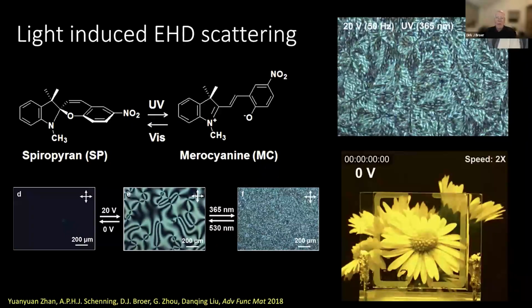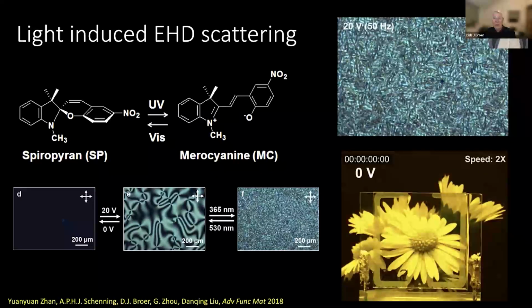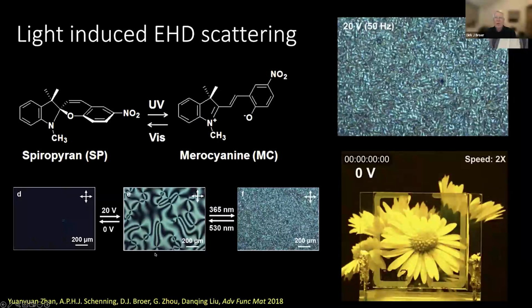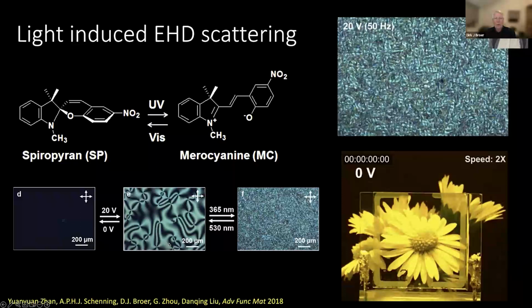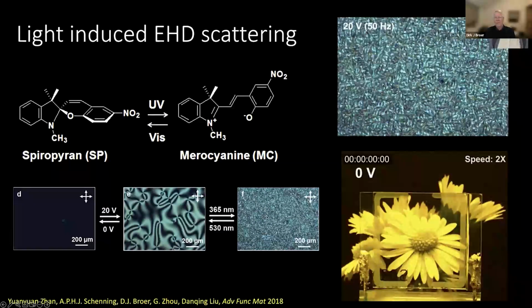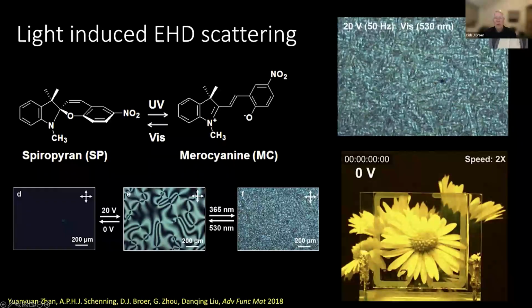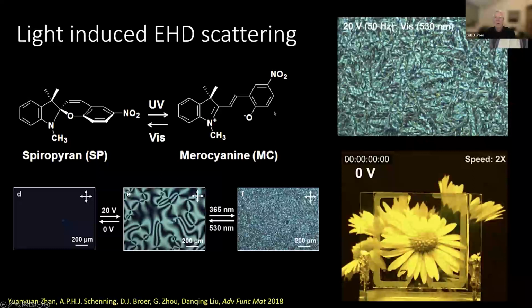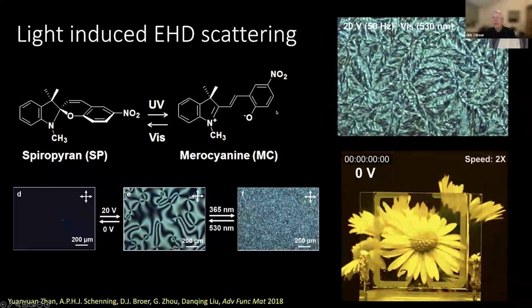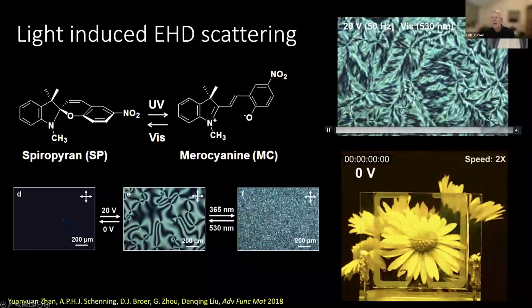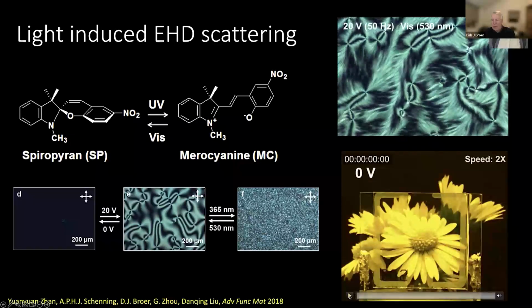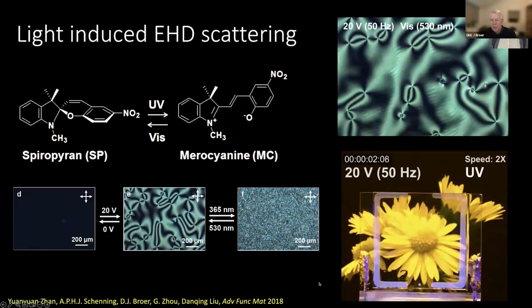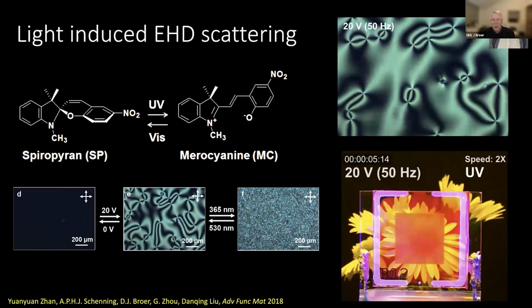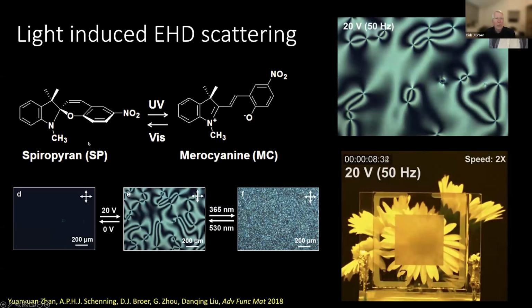Well, now coming a little bit closer to what most people consider a molecular motor, we have here the spiropyran, and spiropyran can be switched between a non-ionic and an ionic shape. And again, we add this molecule in a very low concentration to our liquid crystal, and the liquid crystal then can be switched by light from a planar state to the EHD scattering state due to the motion of this merocyanine molecule in its electrical field. Through the microscope, it typically looks like this. And if you look at the sample itself, if you apply the field, nothing happens. But as soon as you expose it to UV light, you convert the spiropyran to the merocyanine shape. It induces the electrohydrodynamic scattering.